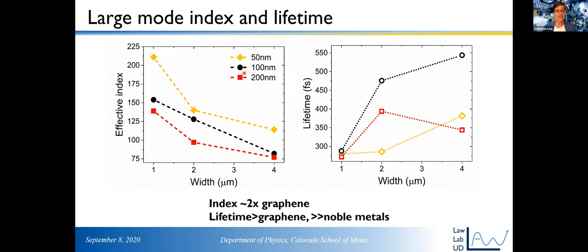Well, the effective index of our bismuth selenide coupled Dirac plasmons is over 200. This is gigantic. This is really, really big. This is about twice what you can get in graphene and much better than what you could get in a noble metal. Normally, when you confine light, its lifetime goes way down. Light doesn't like to be confined. It scatters right out. The lifetime of your plasmon is very, very short.